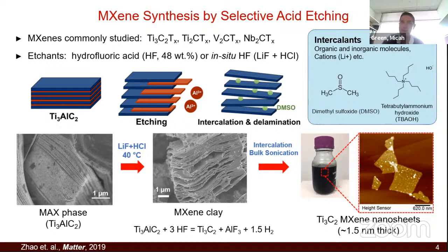Yeah, this is a good question. We have a paper in preparation on this exact question of how does the water interact with the MXene, and also how do antioxidants interact with the MXene. So a couple things to know. One is that the functionality on the MXene is different on the basal plane versus the edge. So for instance, right here, I have a piece of paper. If this is my MXene, the functional groups you have around the edge are different than what you have here on the basal plane. And all the evidence we have seems to indicate that oxidation occurs most heavily at the edges, and it eats its way inward. Even so, it still seems like it's that outer layer of titanium that's being attacked, but one functional group versus another does make a difference.